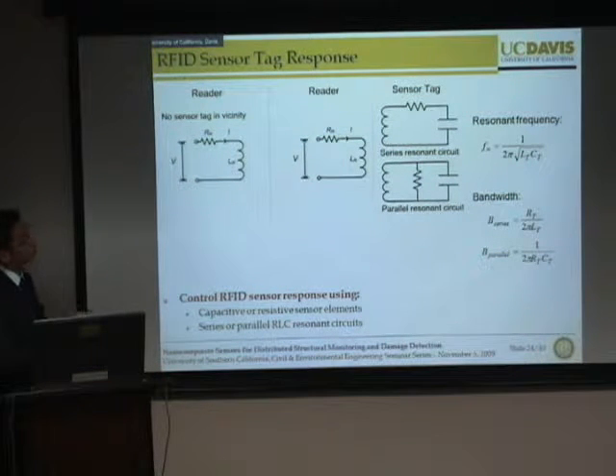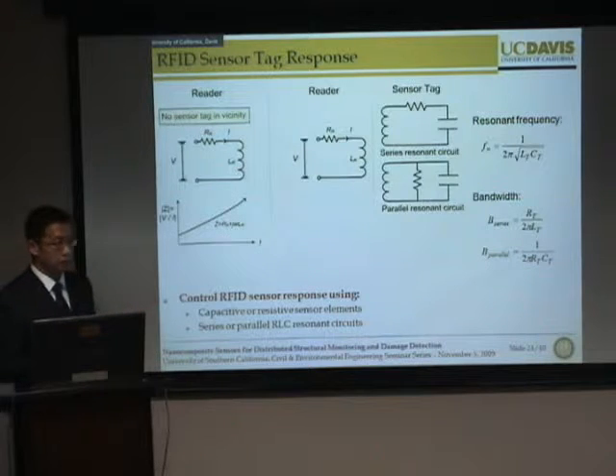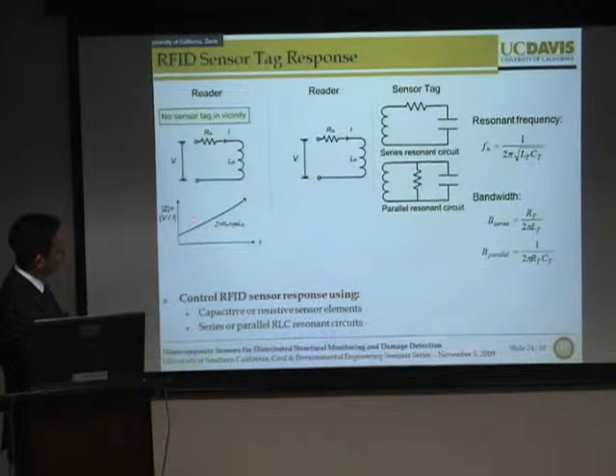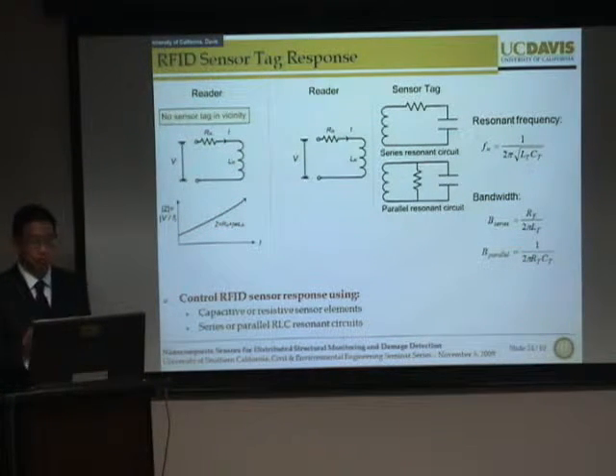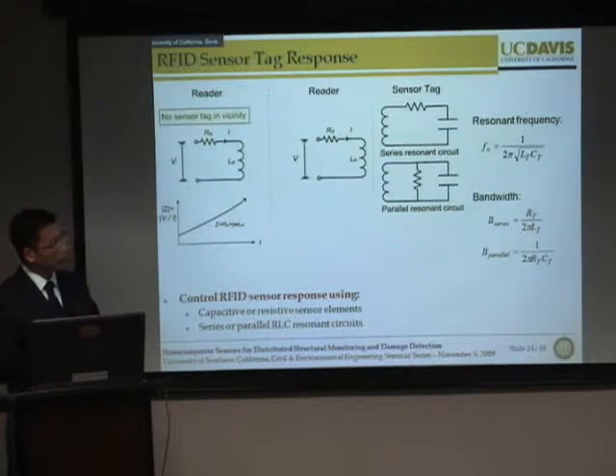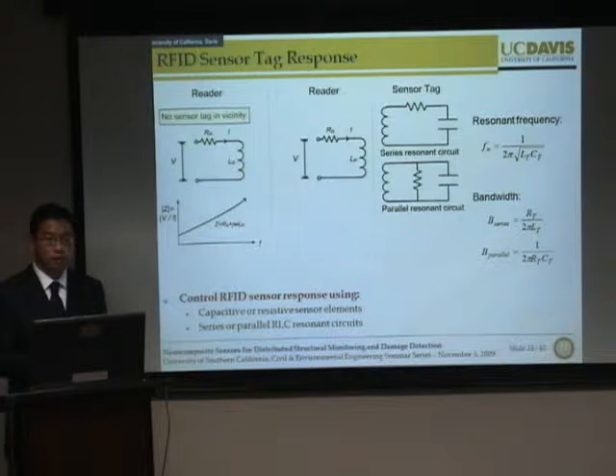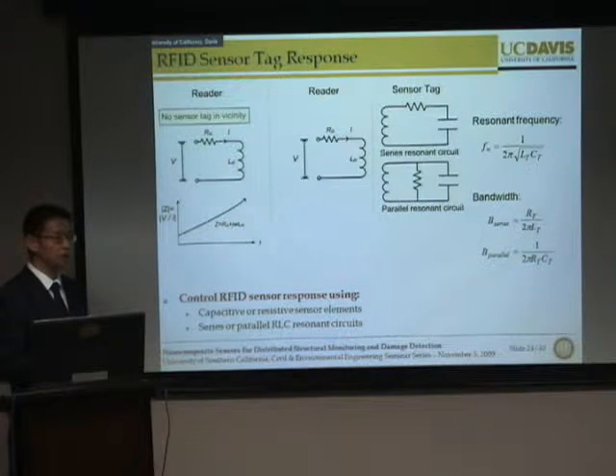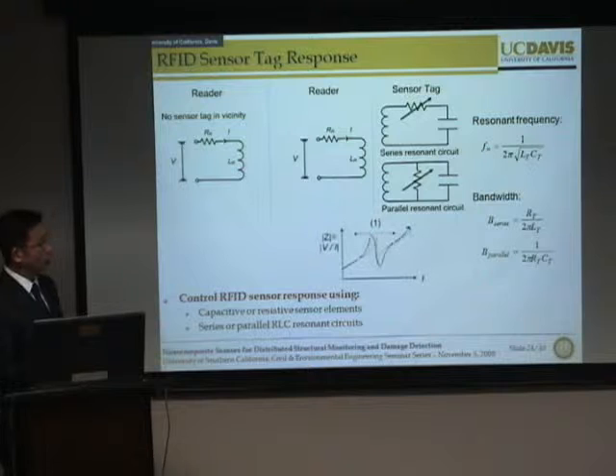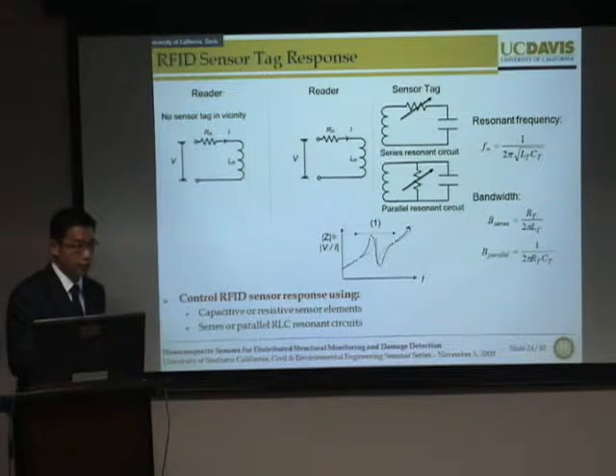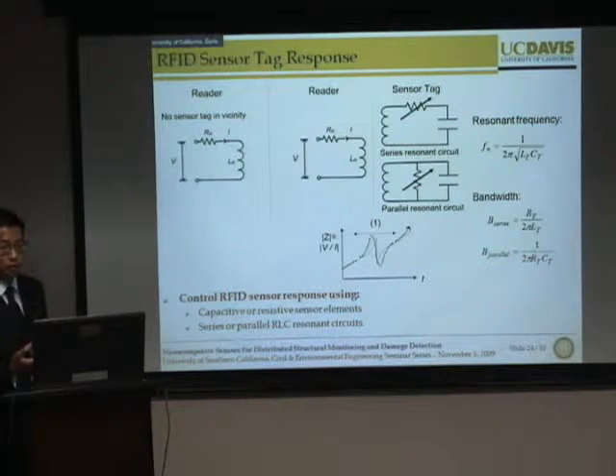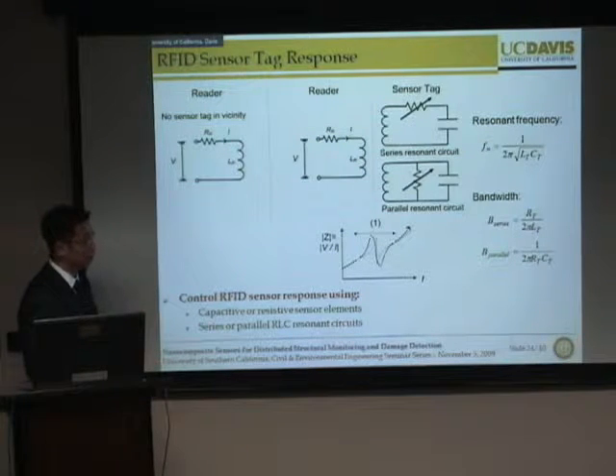Now, first, if we consider just the reader itself where there's no sensor tag, and we measure the impedance of the reader antenna, we see that the impedance as a function of frequency, or the impedance magnitude to be exact, looks almost like a straight line. Now, when a sensor tag, whether it being a parallel resonant circuit or a series resonant circuit, comes within the vicinity of this reader antenna, we immediately see that we can observe resonance as governed by the resonant frequency of your passive sensor tag.